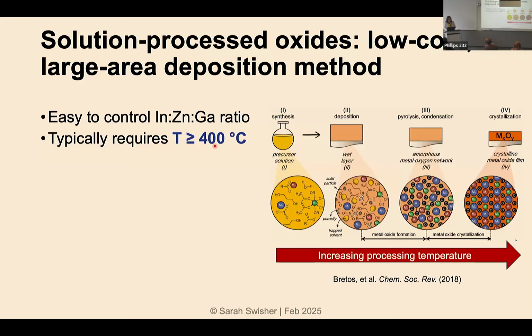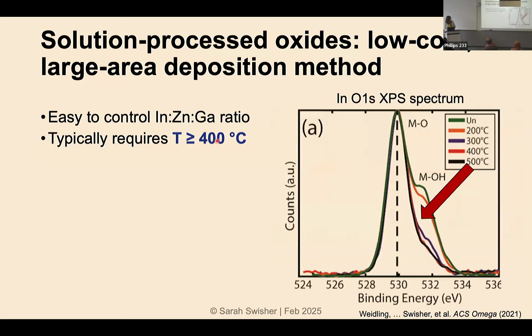And so what we see when we look at, for example, XPS is as we heat this film from the as deposited film shown here in green, where you have this shoulder, as you increase the temperature, what we see is that the oxygen is bonding more to the metal and less to a metal with a hydrogen. So as we increase the temperature, we're getting more of this desirable metal oxide and less of this undesirable metal hydroxide. Okay, so if we don't heat it enough, we're not going to actually get the semiconductor that we want.